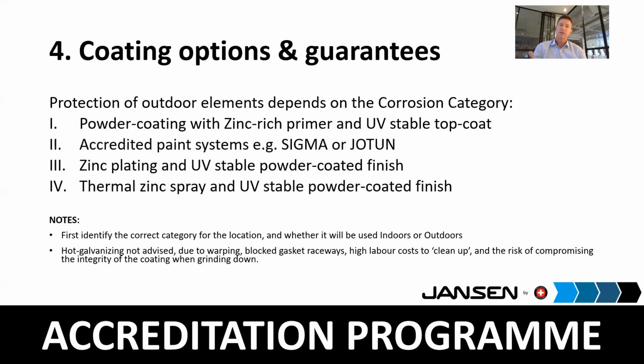You know that most steel products in this country, you have to have self-adhesive gaskets, or you'd make some plan with the gaskets. But the Jansen systems have a gasket raceway that you press or roll the gasket into, and they can get blocked up with welding spatter, or in this case, with hot dip galvanizing. Obviously, hot dip galvanizing also costs a lot of money to clean up, and there's a risk of compromising the integrity of the coating when grinding it down.